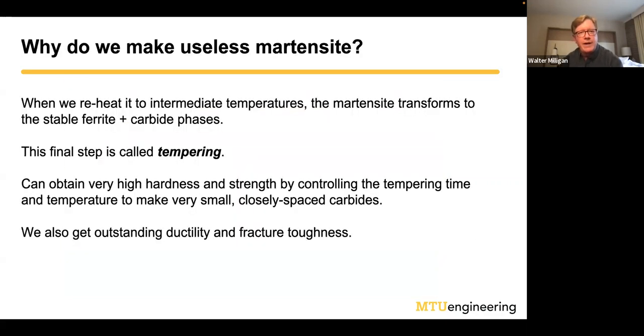So why do we want to make useless martensite? The reason is we can take that martensite and reheat it to an intermediate temperature. And these temperatures are typically around 200 or 300 degrees C, the kind that you could get in your home oven, like a pizza baking temperature. And what happens is the martensite transforms to the stable phases of ferrite and carbide. And that final step is called tempering. So it's kind of like the steel was in a bad mood, so we had to temper it. I think that's where it came from, just shop jargon from 200 years ago or whatever.